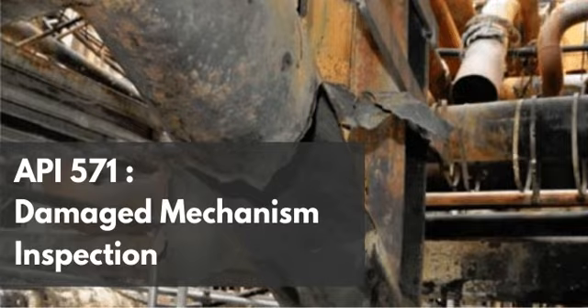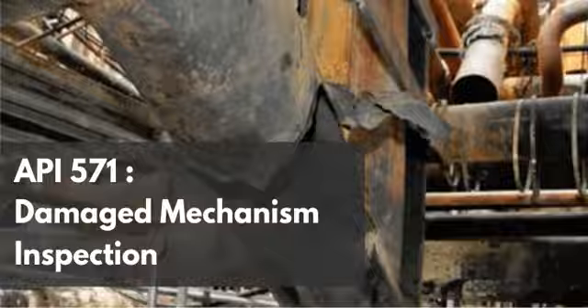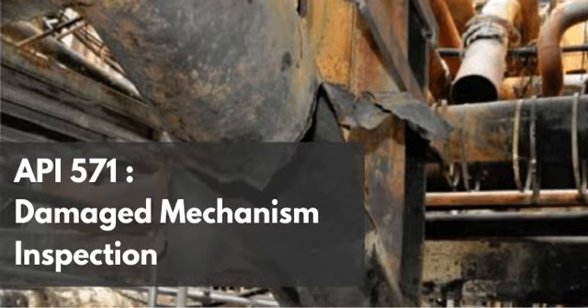The only mitigation is mechanical dilution. The equipment must be meticulously water-washed, circulating massive volumes of clean water to physically flush every single molecule of residual amine out of the scale and crevices before any thermal energy is introduced to the steel. It's a profound reminder that we are dealing with systems that are incredibly sensitive to both mechanical history and chemical state. The intersection of thermodynamics, metallurgy, and operational flow is truly unforgiving. But it is entirely manageable when you rigorously adhere to the engineering controls, the strict PWHT parameters, and the advanced NDT inspection protocols dictated by the standard.